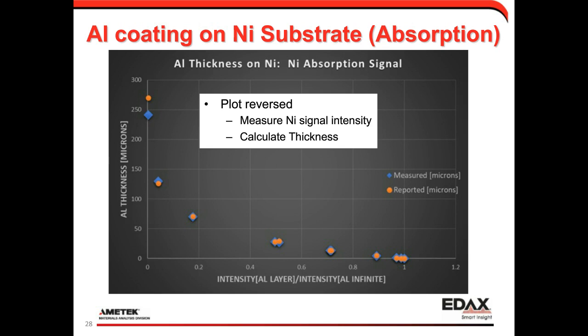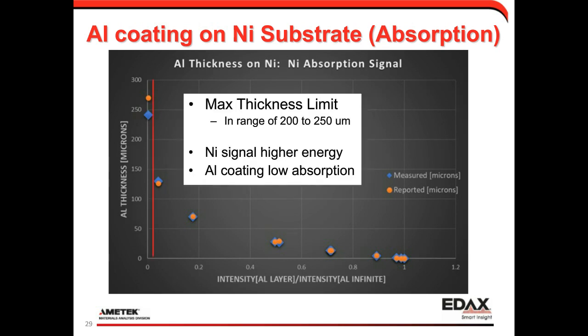And you can see we're getting pretty good results all the way up to, on this chart, 140 microns. Here I've just stacked some reasonably thick aluminum foils together, measured their thickness with a micrometer, and used that as one of the points on the plot here. And so our high-end thickness range here is around 200 to 250 microns of aluminum, using the nickel as a gauge for how thick is the aluminum coating. This is because nickel is a higher signal energy and because the aluminum coating is not an effective absorber for nickel. So our high-end range in measuring aluminum coating thickness on the nickel is much higher than in emission mode. The physics for this situation are a little bit different.